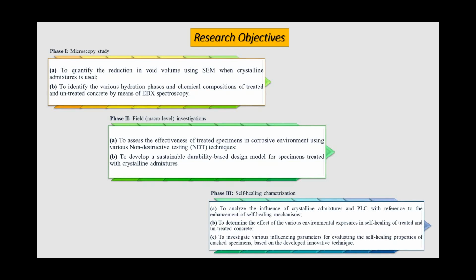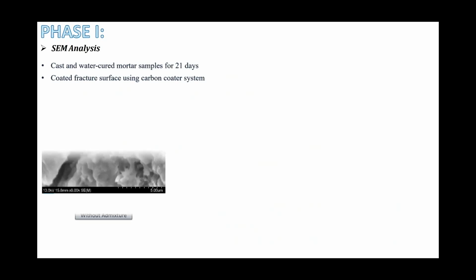So I'll start with phase 1 of my study, which, as I mentioned, is the microscopy. First of all, I used scanning electron microscopy to see the structure and morphology of my samples. I cast some mortar, broke them, and coated the fracture surface. You see the difference between the control samples, which don't have an admixture.